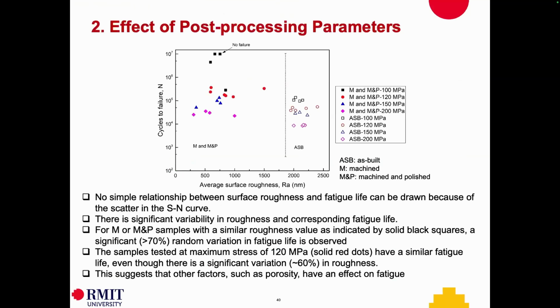Then this is a summary which summarizes the data from machined and polished for these 4 stress amplitudes. With the as-built, you can see the as-built have a clearly low fatigue life. There is no simple relationship. Significant variability was observed in surface roughness and corresponding fatigue life. But with the machined and polished samples, with the similar roughness values, which is to say solid black squares, the fatigue life can be at least 70% variable. Even the samples we tested at maximum stress, which is the red dots here, have a similar fatigue life, although there is a significant variation of roughness.